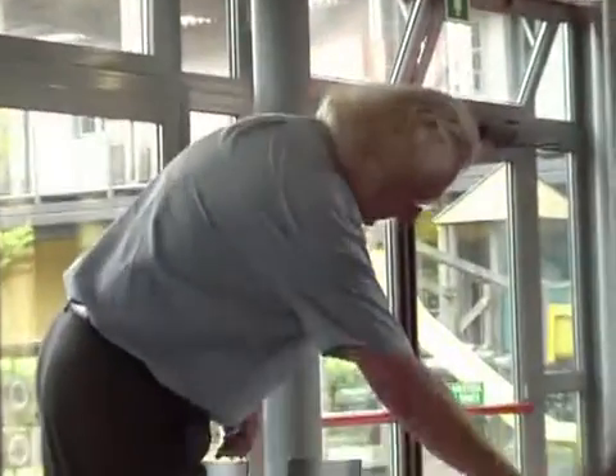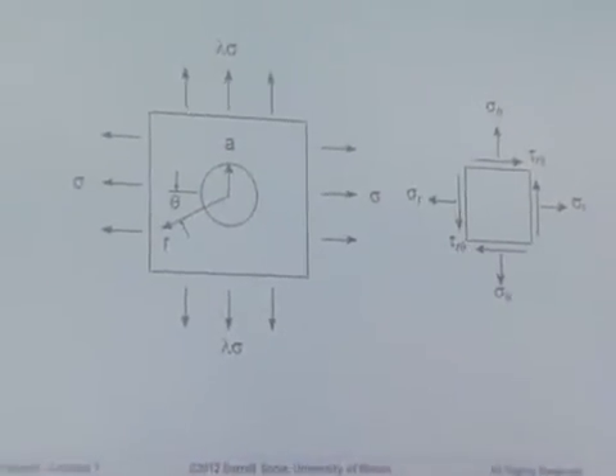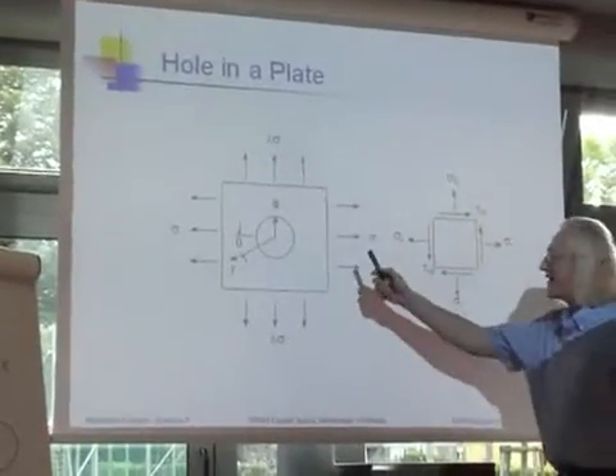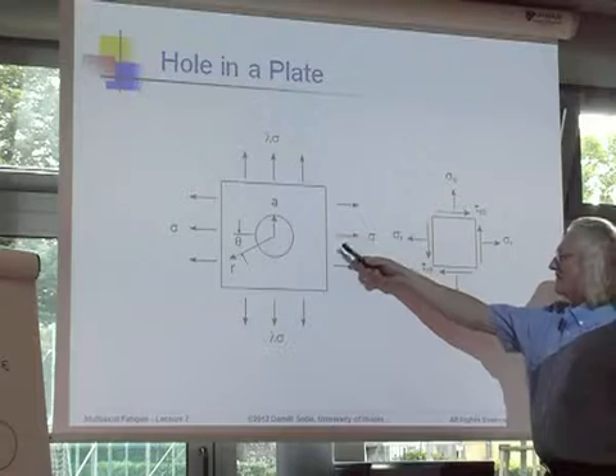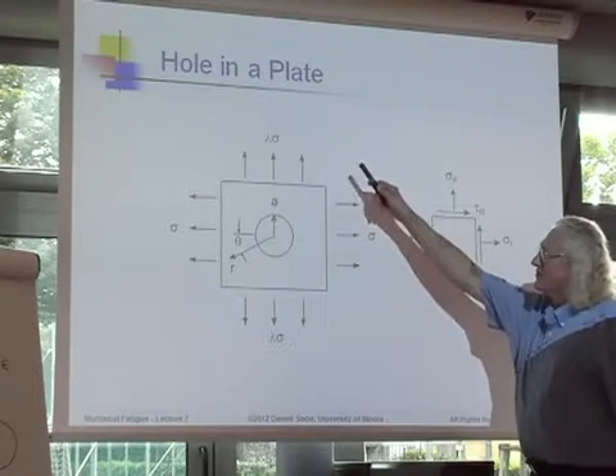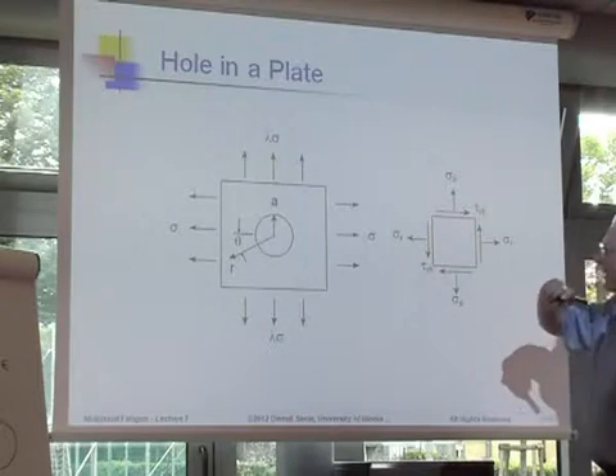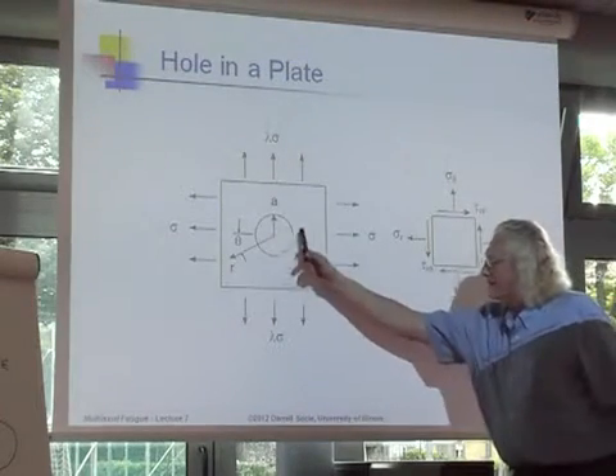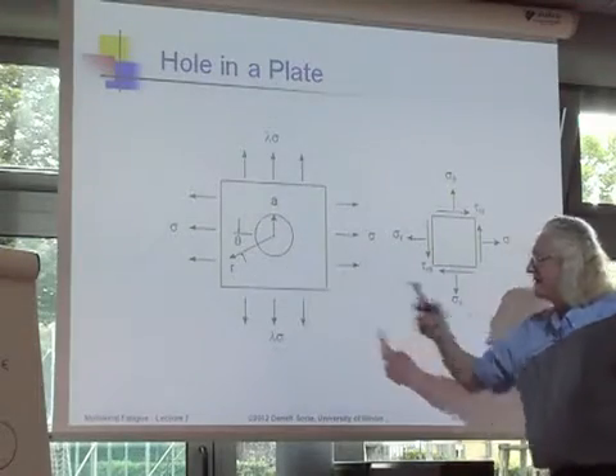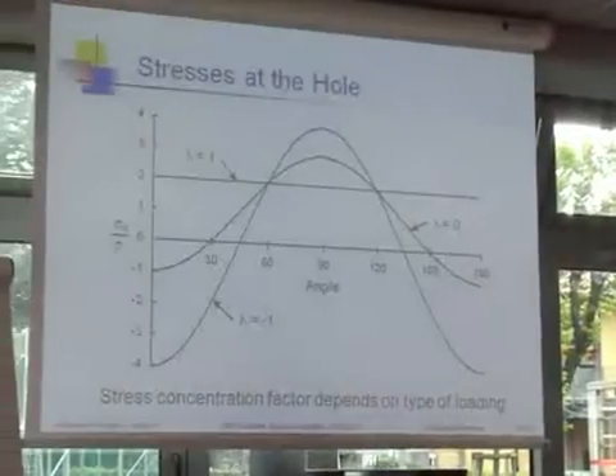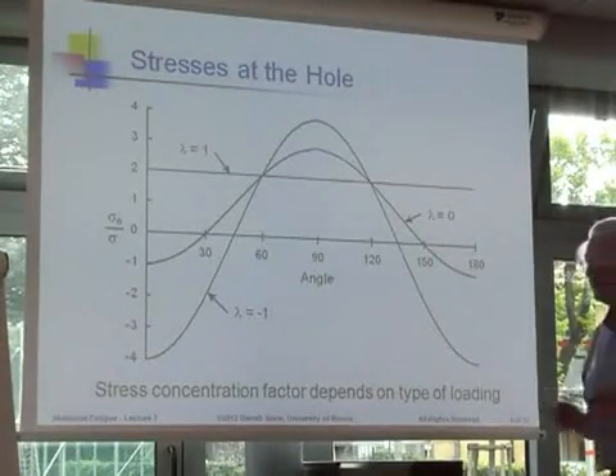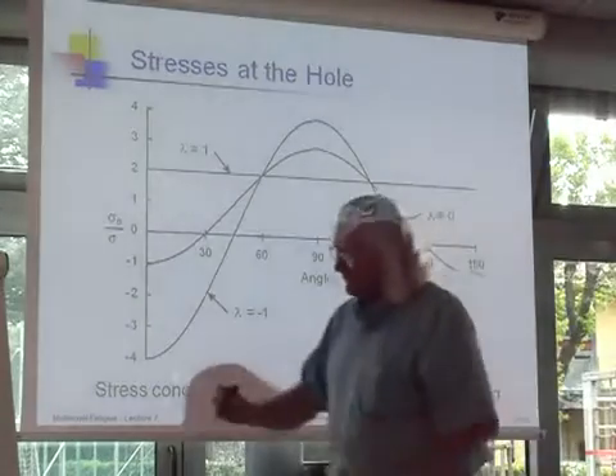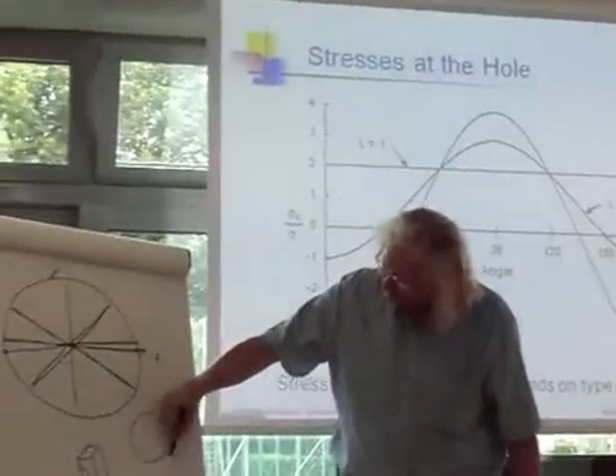So we can just look at this a minute. There's a hole, and I showed this kind of slide before when we looked at a crack. So I put a hole in there, and I load it with the stress in this direction and some stress in the other direction, which is a constant lambda times this one. And okay, there's the hole, and I can look at the stress fields everywhere around that hole. If you just look around the edge of the hole, then if you have biaxial tension, the stresses are constant everywhere. Right? So everywhere around the edge of the hole, they're always the same.